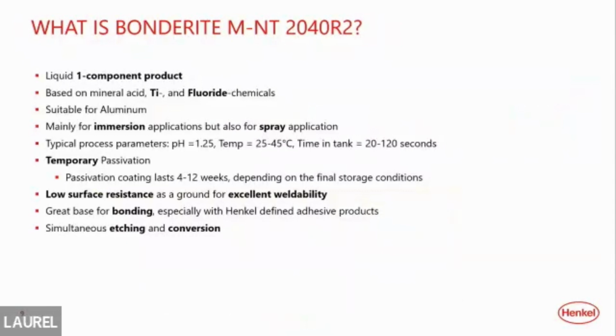This is the product. Now, I know we don't want to really get into products and all that, but it's titanium fluoride based. It is aluminum only. It is mainly for immersion, but it can also be done in a spray application. However, the coating weights will get higher in a spray application, so we have to tweak it a little bit if you run it spray. It does run on a low pH side.